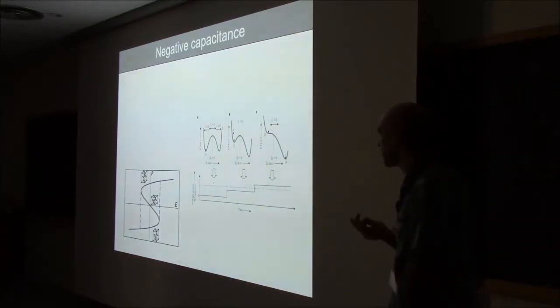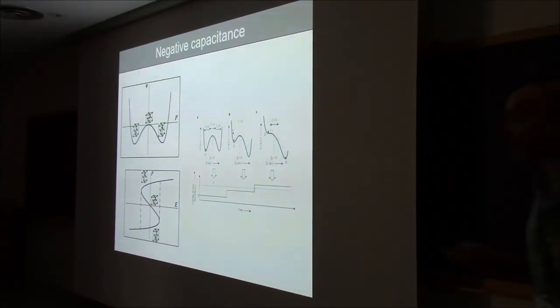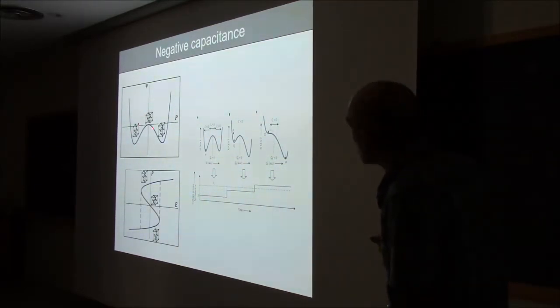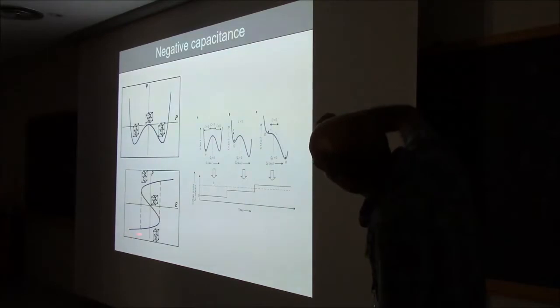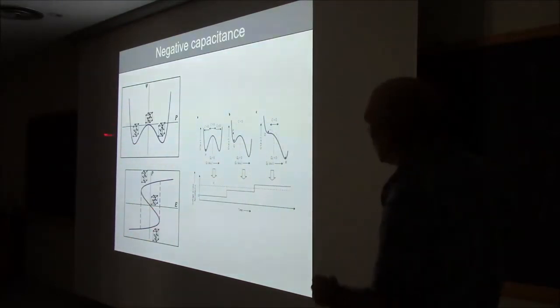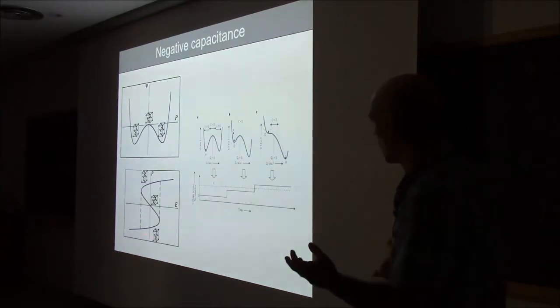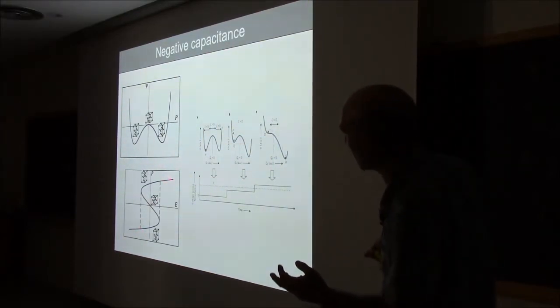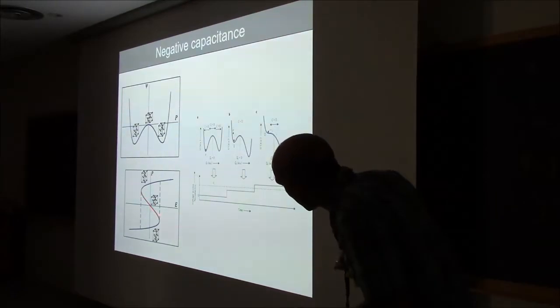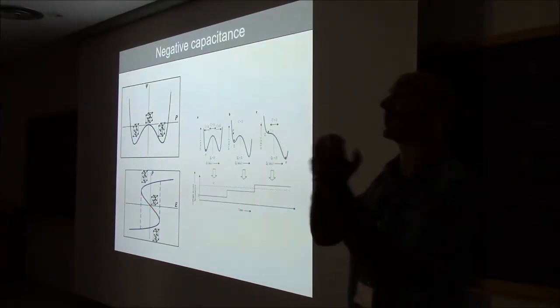Okay, so domain walls, what else have I covered? Negative capacitance. So I'm now in the section where I'm going to blurb about things that are fashionable in ferroelectric research. I mentioned earlier negative capacitance, which is a hypothetical state that would exist if you could stabilize your material here. If you calculate the electric field as a function of polarization, it has this S shape. You cannot access this normally because when you switch polarization, you switch from the minus polarization to the plus polarization. But if you could access this area here, the derivative of the electric field with respect to polarization is negative.